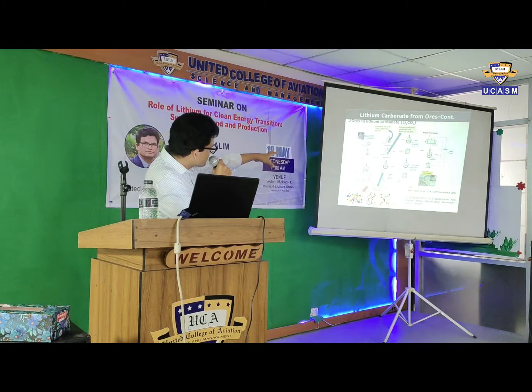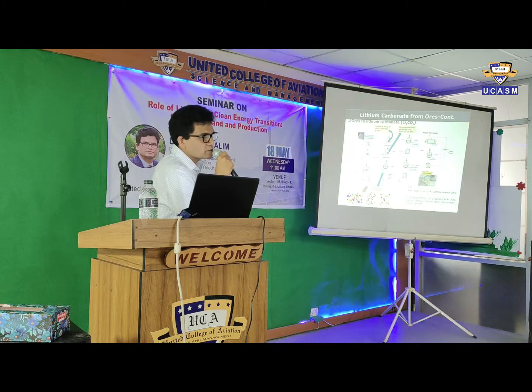These are the process steps we do. First, on the left side, we do the mineral processing to get the concentrate. What is the concentrate? Initially in the rock there was 1% lithium oxide. We increased the percentage to 6% by doing mineral processing using dense media separation, or heavy media separation, because the density of this spodumene is much higher than the others.